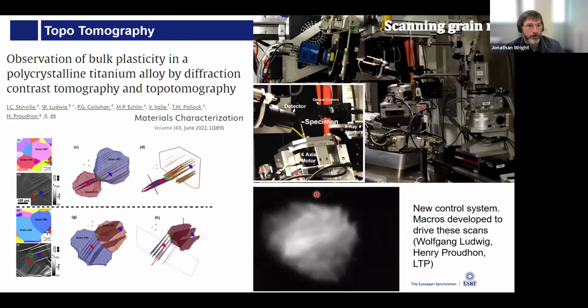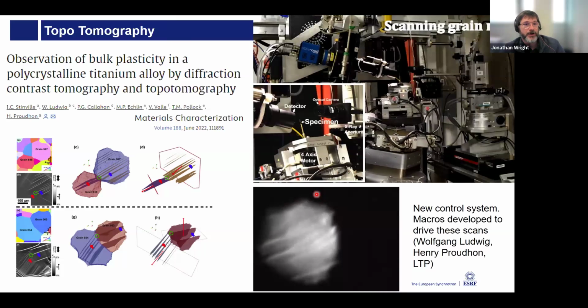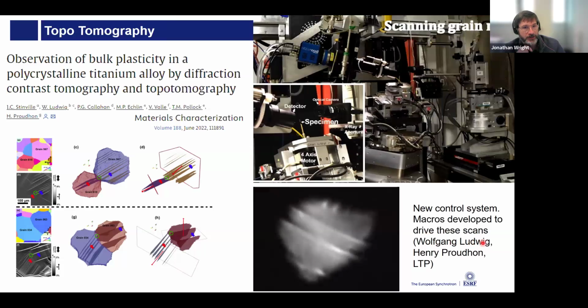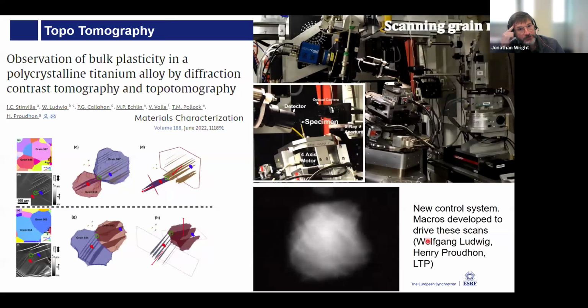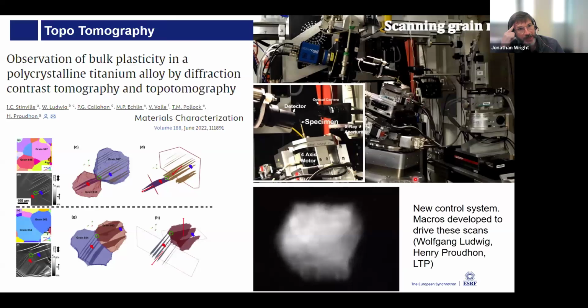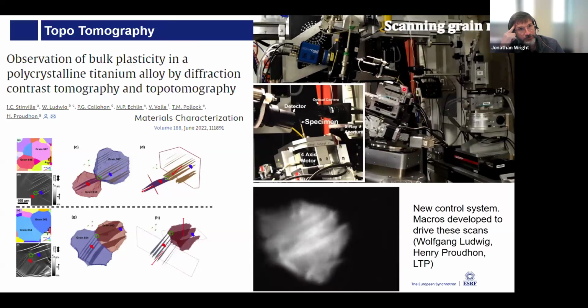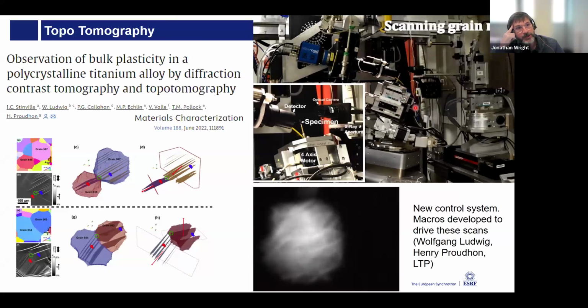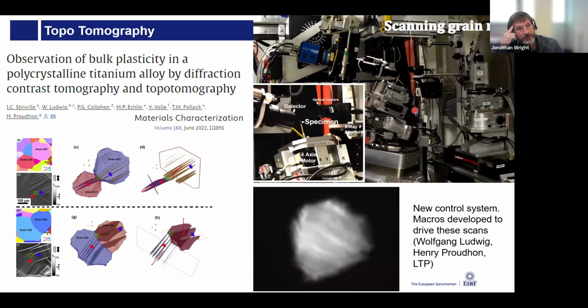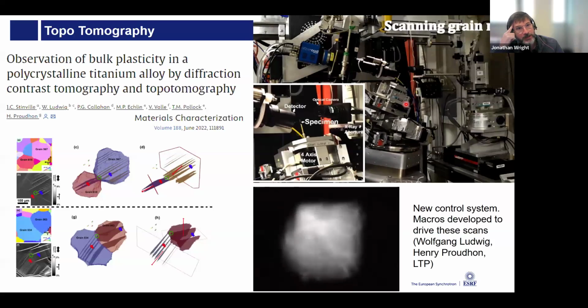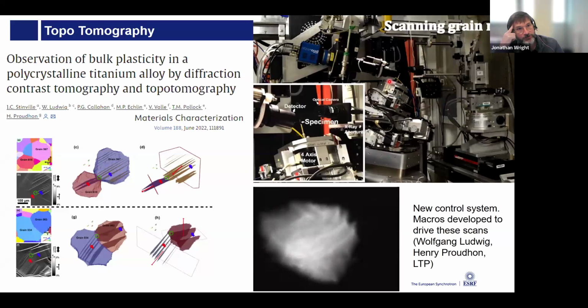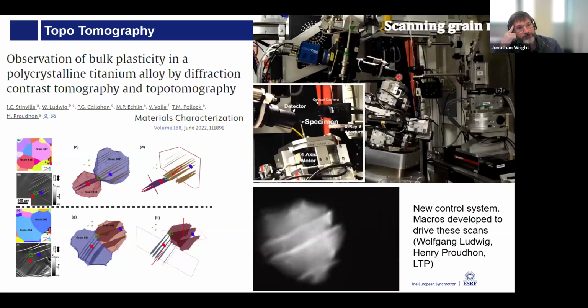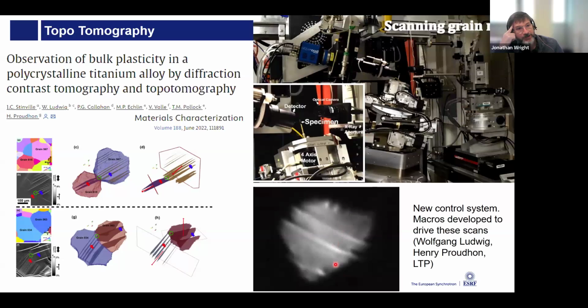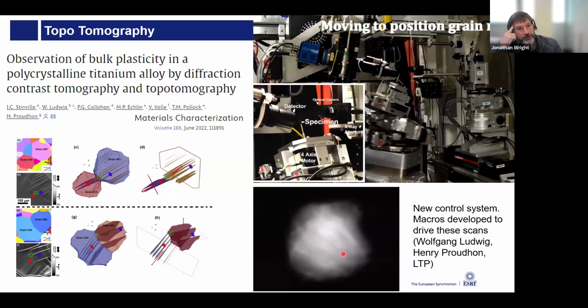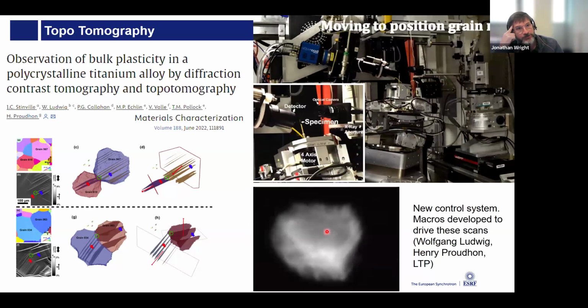This is called topotomography. This is something where Wolfgang Ludwig has been a key developer, and recently, together with Henri Proudhon, they've adapted all of the macros that drive the diffractometer to do this. So they work with our new control system, and they're all optimized for BLISS. So at the top, you see how the diffractometer is moving, and it's rotating around a scattering vector. And that's the scattering vector of this particular crystallite, this particular grain that's inside the sample.